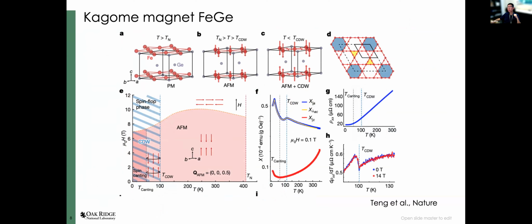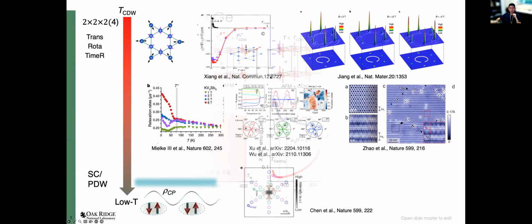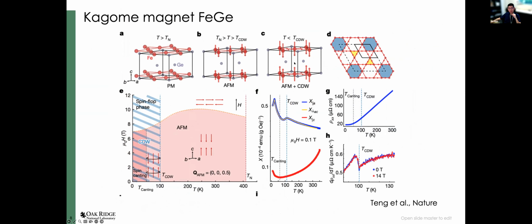Later, I think there was an important discovery from Rice University, from Pengcheng Dai's group. He found in a Kagome magnet, iron germanium, there might be some similar physics. So here shows the crystal structure of iron germanium at a very high temperature, around 400 K or so. There's a paramagnetic to A-type AFM phase transition. And if you go to an even lower temperature, all of a sudden you have a CDW transition temperature, which is rarely seen in materials. And after the CDW transition, the neutron scattering group found that the local spin moment is enhanced.